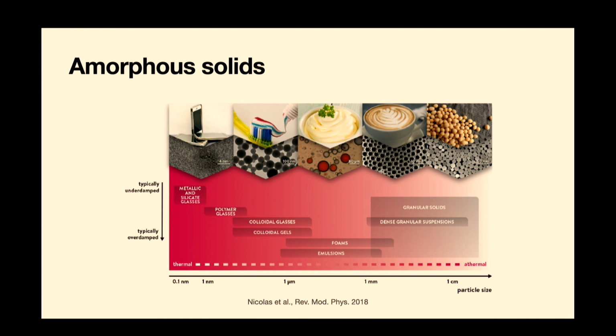And we're going to mainly look at the athermal end, where the particles are big enough that to a first approximation you can neglect thermal excitation. So you could think of granular suspensions, but also foams and emulsions with reasonably big droplets are in that category, where kT is much smaller than, say, the typical surface energy of an emulsion droplet or a foam bubble. Okay?